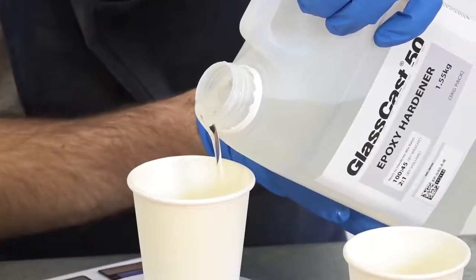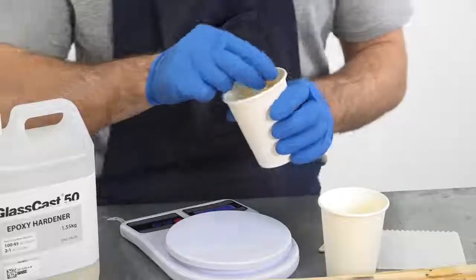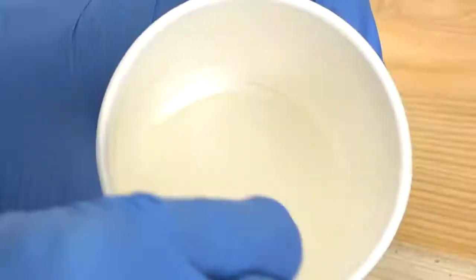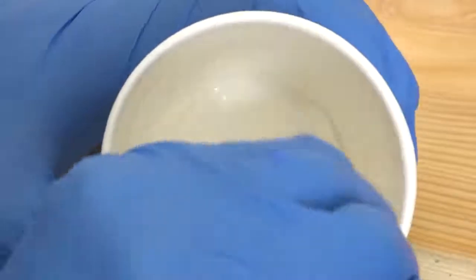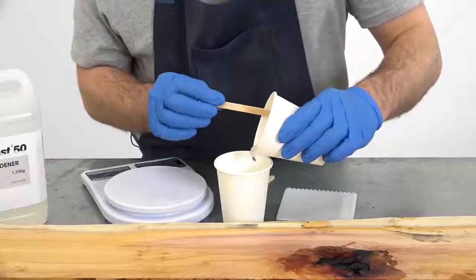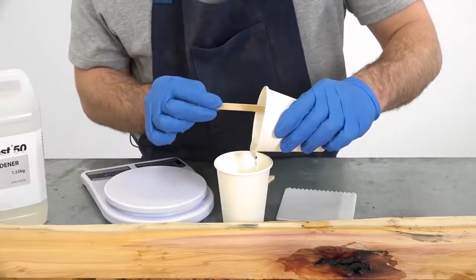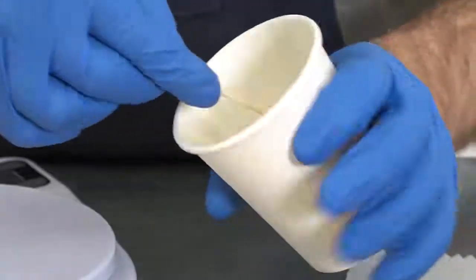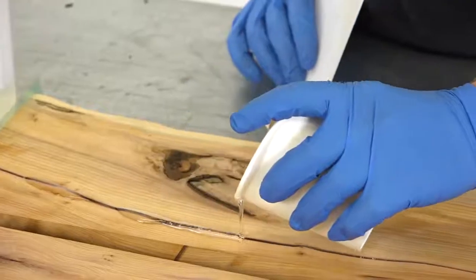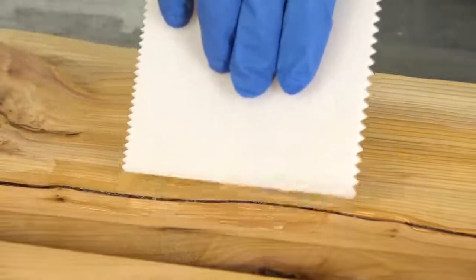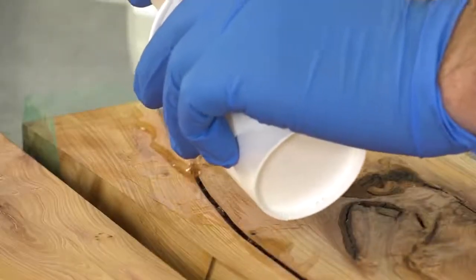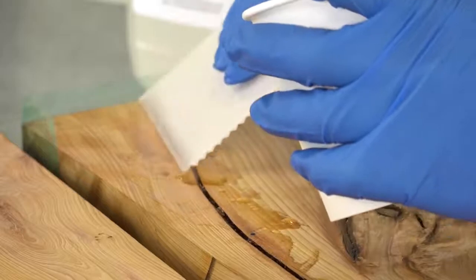For this small mix, I'm going to use the 100 to 45 by weight mix ratio. I'll keep things simple with 100 grams of resin and 45 grams of hardener. Although this is only a small mix, when mixing epoxies, it's best practice to double pot, mixing thoroughly once in one pot and then transferring to a second pot and mixing again, ensuring that no unmixed resin can find its way onto the job.